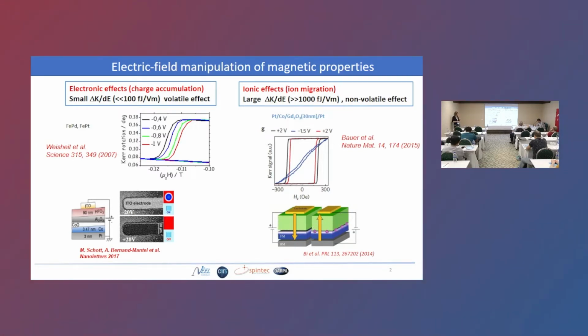Other groups have been showing these effects, always using a gadolinium oxide layer. The effect was shown to be non-volatile, so when you remove the electric field, the magnetization state of the sample stays the same. The effects are reversible, and this was associated to the migration of oxygen ions through this gadolinium oxide layer that is, as I say, an ionic conductor, so that the chemical structure of the top cobalt interface is modified. So how can we explain this?